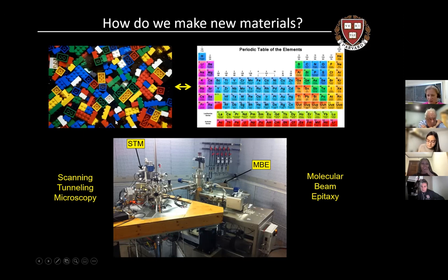And so instead of relying on some kind of chemical process in thermodynamic equilibrium, we're actually doing a physical deposition where we can build one layer at a time, even structures that might not occur naturally in nature. And once we have grown that material, we can transfer it through ultra high vacuum and down into our microscope, which is off screen here. And we typically are doing our imaging at 4 Kelvin, very low temperatures, where we can get very high energy resolution on the electron states.